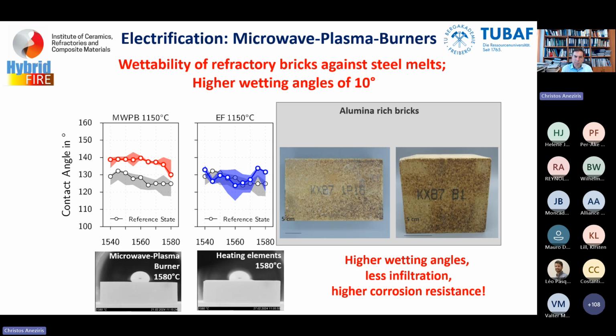We have seen this by using alumina-rich bricks as a lining in a ladle, and we have gone into a heating microscope. On the one hand, a surface treated by a microwave plasma burner, on the left below at 1580, and on the right by using normal electrical heating elements in an air atmosphere. And we have seen that the wetting behavior is completely changed. That means we have less wetting, that means higher wetting angles, that means less infiltration, and at the end of the day, also higher corrosion resistance.